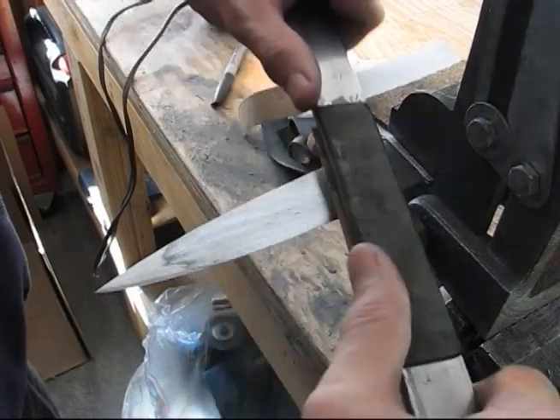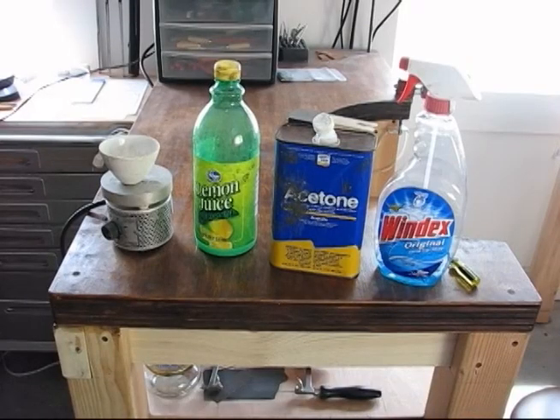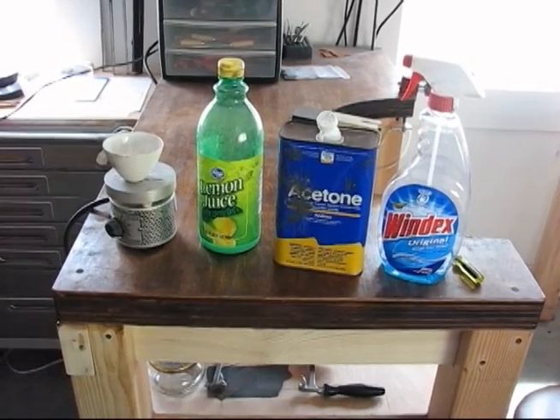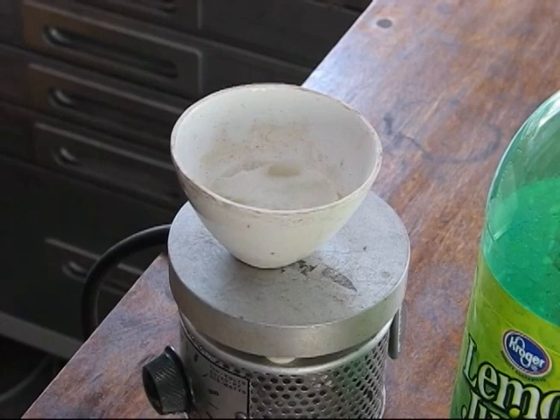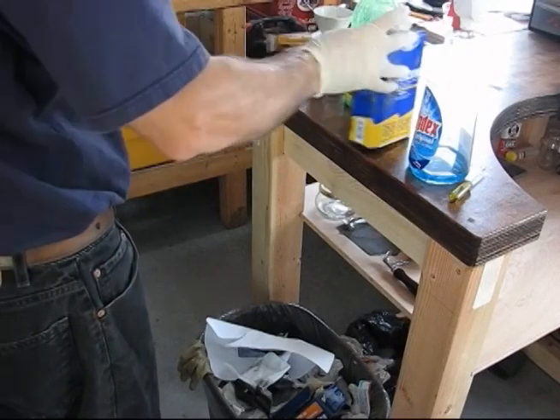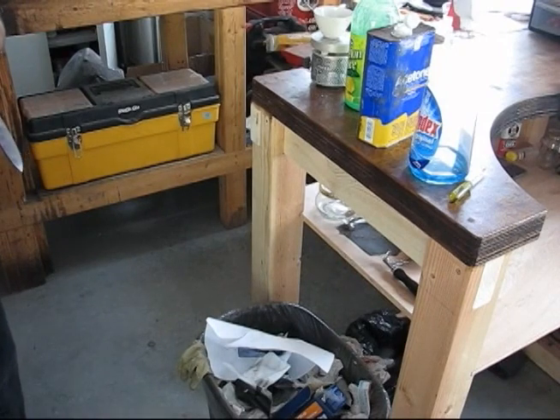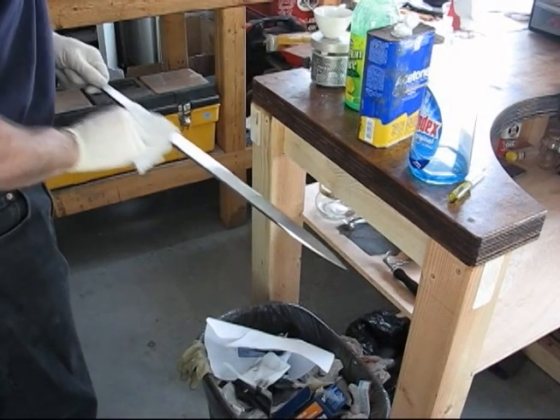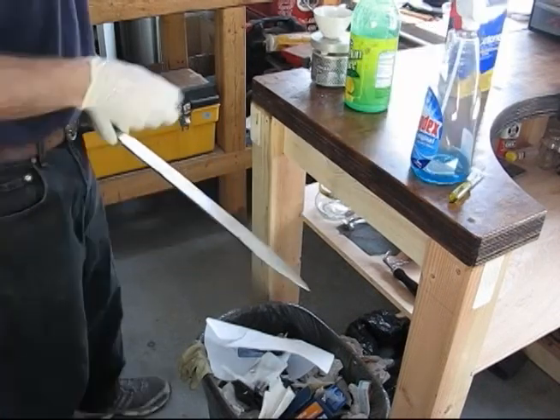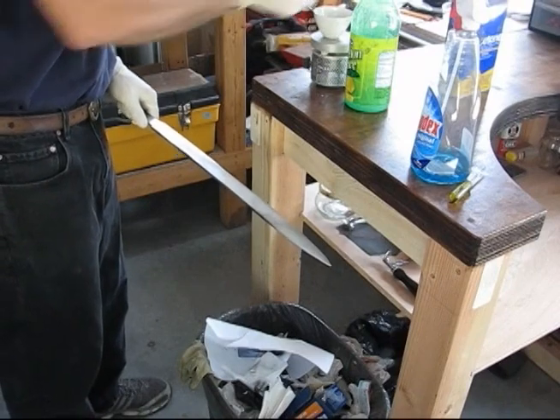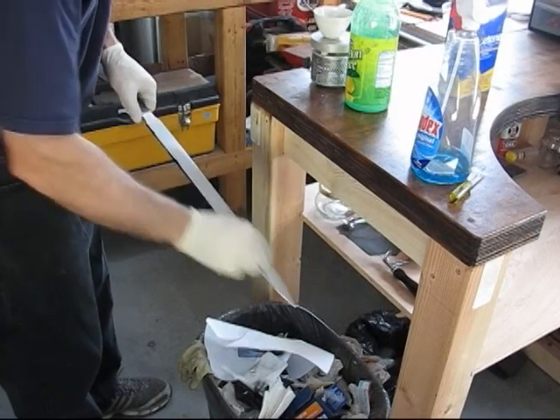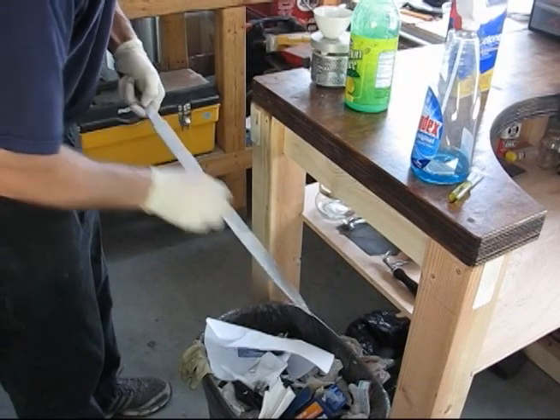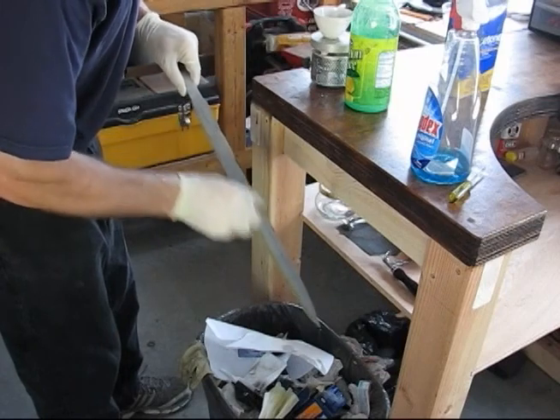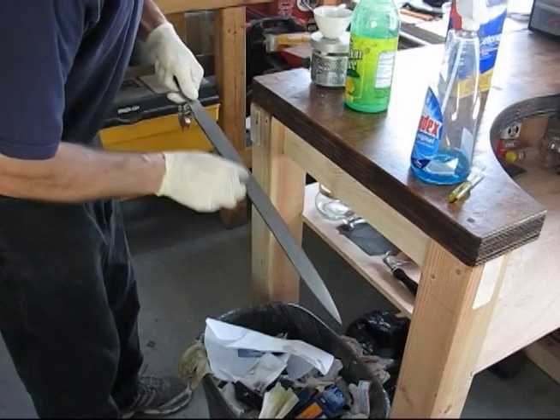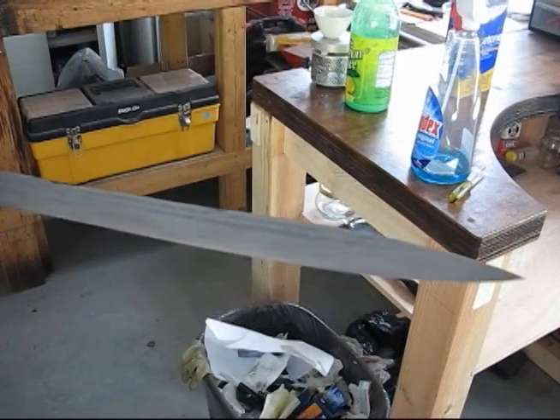After reaching a 220 grit polish using sandpaper, Jesus cleans the blade with acetone and etches the blade with hot lemon juice. After a few minutes, a hint of the final pattern of the blade can be seen. Everything seems to be in order to move on to the next step.